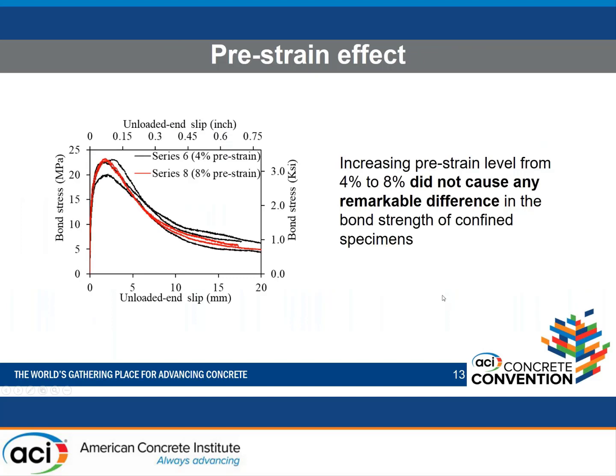As I said before, we did one series with a different pre-strain just to see if there is any influence. And as you see here, there's not much of an influence. The 4% and the 8% are very close in terms of behavior, and this means that they have very similar bond strengths.